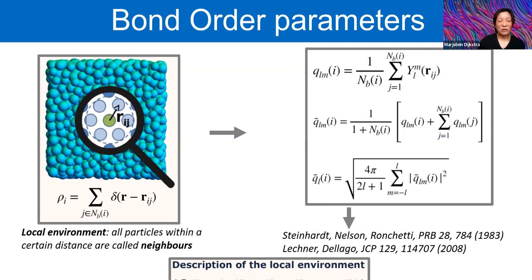We first have to define the local environment, which is just defining the neighbors of a central particle. The simplest way is to use its radial distance. So all the particles within a certain radial distance are called neighbors, and there are many more algorithms to do this. These neighbors you then expand in a set of spherical harmonics.